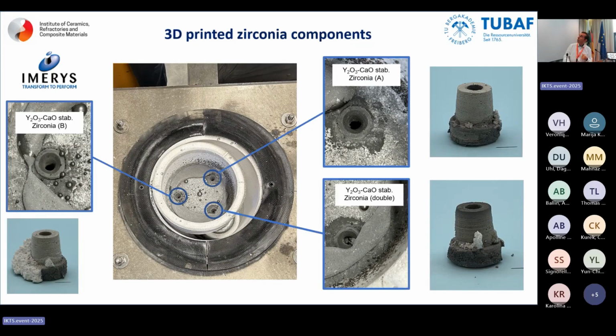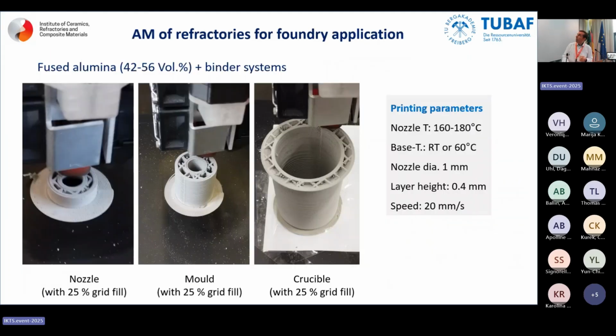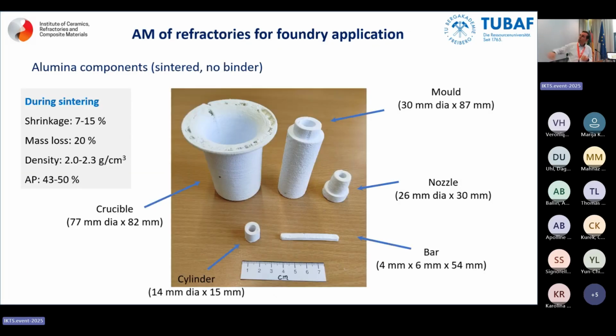Yes, you survive thermal shock, and you survive the thermal shock several times, in spite of the fact that it is a fine-grained zirconia material as it is used in solid oxide fuel cells. Of course, not scandium and this kind of thing. It's magnesium or calcium or yttrium. And of course, you can design everything that you need. This is a fused alumina system. You can make nozzles, crucibles, and you survive.